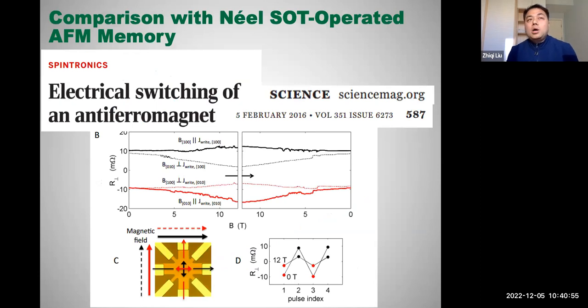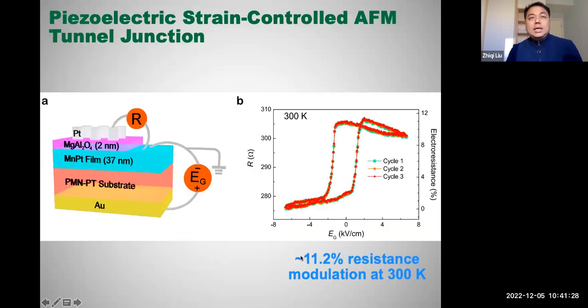If we compare our electric field controlled antiferromagnetic memory device with the so-called electrical current controlled one, because of the Lorentz force under strong magnetic fields, the electrical current controlled one could not work. For example, at 12 Tesla, the writing is almost gone, so you don't have clear high and low resistance states. I think that's a big advantage for the electric field controlled one.